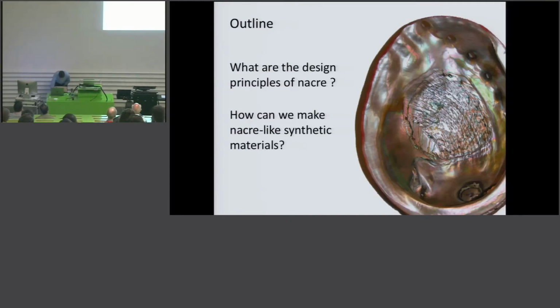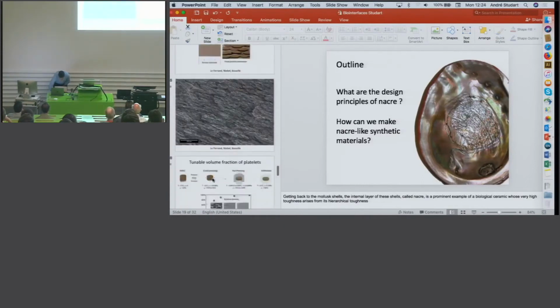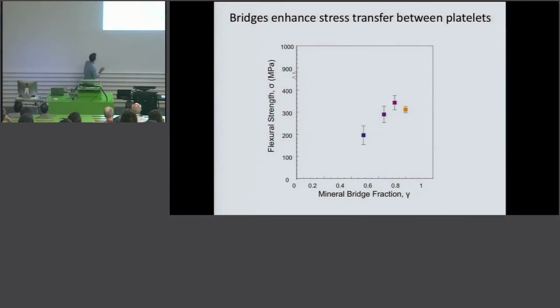And we've developed a way to produce materials, starting off with very thin and small platelets, and create these mineral bridges. So this is the final result. What we do is the following. We buy platelets that are already very thin and very elongated. But we know that the polymer around it, just like in the seashell, is not stiff enough to transmit a lot of shear forces, so we also add mineral bridges. So the material looks like this.